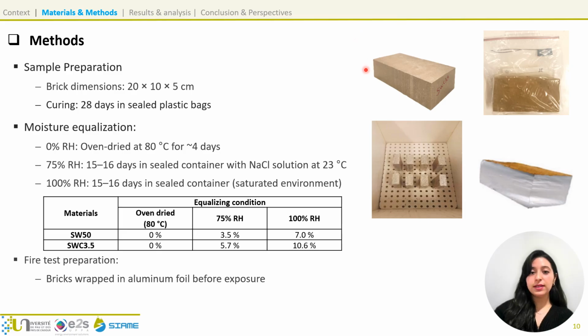Our samples were manufactured as bricks of 20 by 10 by 5 centimeters and cured for 28 days in sealed plastic bags. Moisture equalization was then performed under controlled conditions: 0% relative humidity by oven drying at 80 degrees Celsius for 4 days, 75% relative humidity in sealed containers with a sodium chloride solution at 23 degrees Celsius, and 100% relative humidity in saturated conditions, both for 15 to 16 days. The corresponding water contents for each condition are summarized in this table. As expected, higher relative humidity leads to higher water content, and cement-stabilized bricks retain more water compared to unstabilized ones. Before the fire test, all bricks were wrapped in aluminum foil to ensure uniaxial heat and moisture transfer.